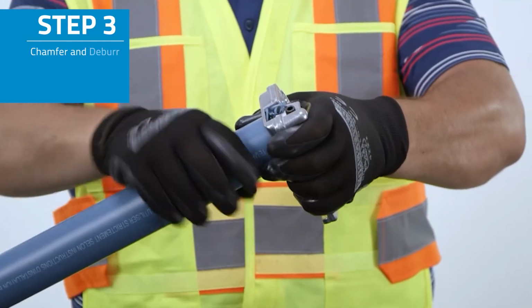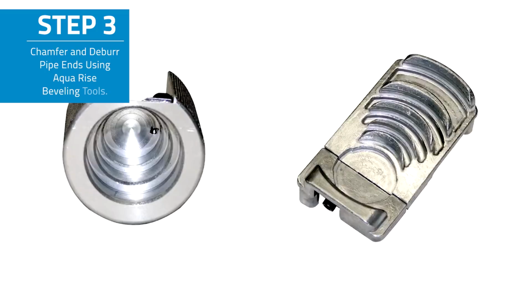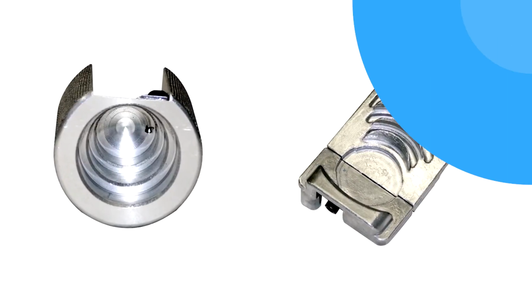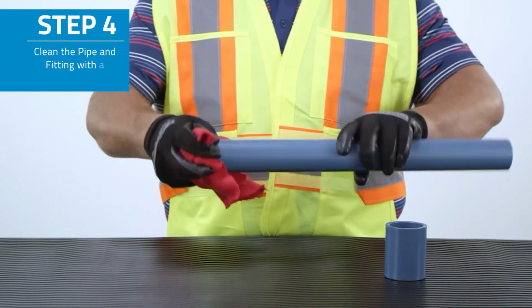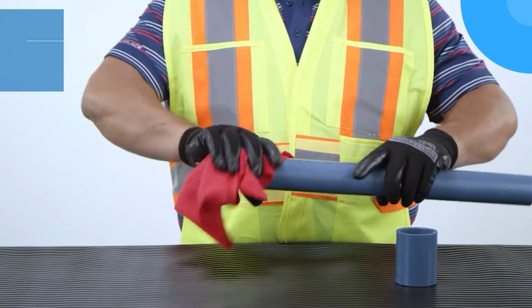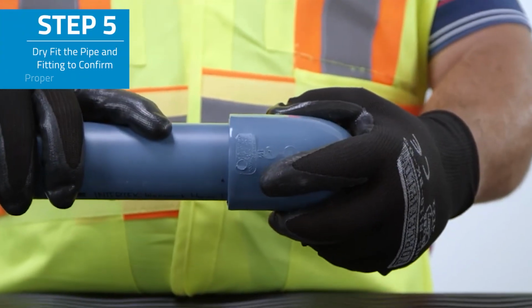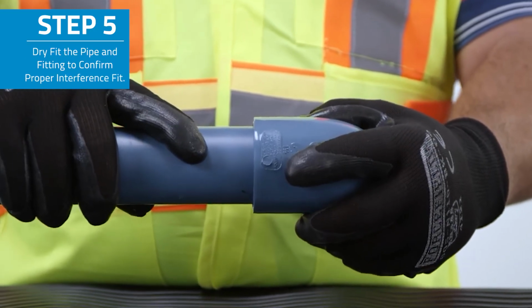Step 3. Chamfer and deburr pipe ends using AquaRise beveling tools. Step 4. Clean the pipe and fitting with a clean rag. Step 5. Dry fit the pipe and fitting to confirm proper interference fit.